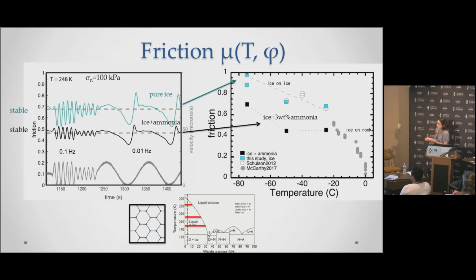And so one thing that was kind of surprising to me is that having that melt there didn't make it respond like this. It didn't just drop drastically. It had a very controlled response. So there's still a lot of ice contact probably during the sliding, but yet some weak spots with the melt that caused this reduced friction.